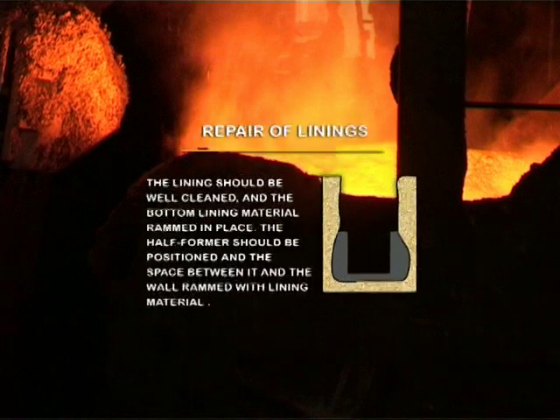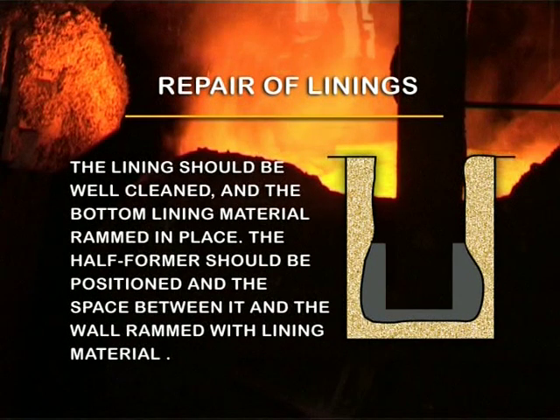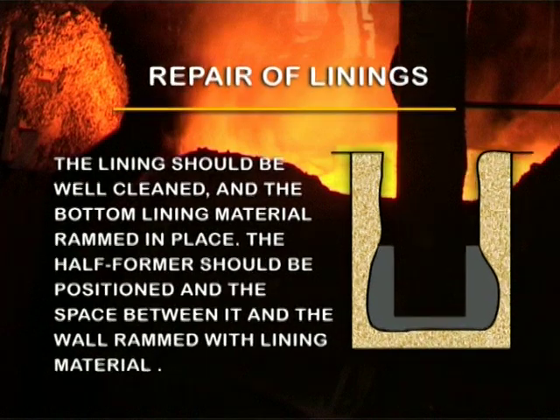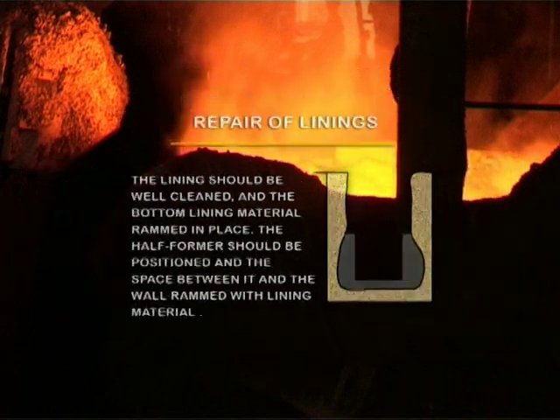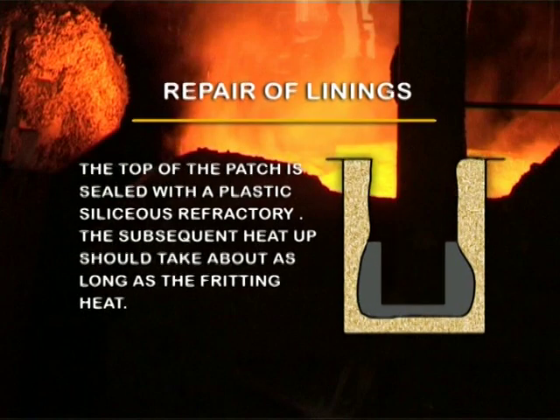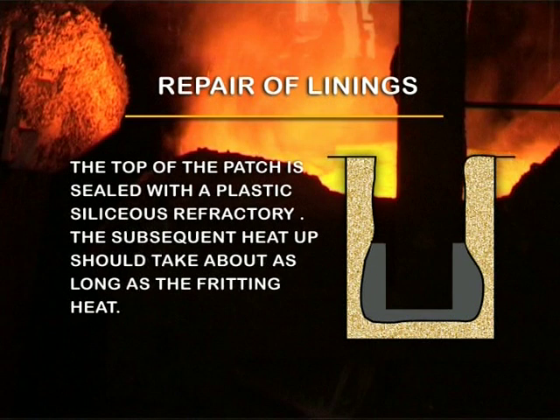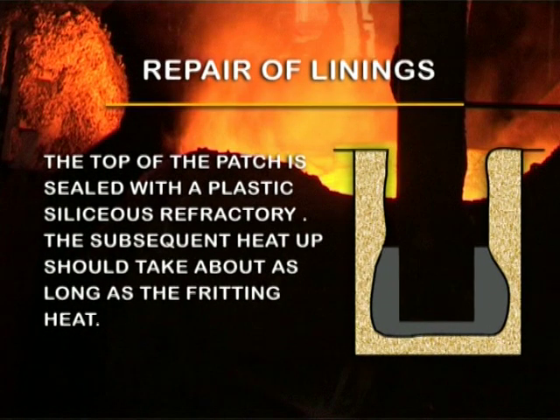The lining should be well cleaned and the bottom lining material rammed in place. The half former should be positioned and the space between it and the wall rammed with lining material. The top of the patch is sealed with a plastic siliceous refractory. The subsequent heat up should take about as long as the fritting heat.